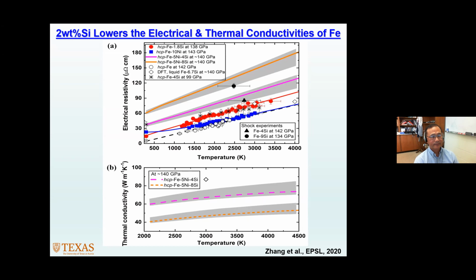And here you're talking about the solid, though, and you need to be considering the fluid, the liquid as well. Yes, I totally forgot to mention that. For Earth's outer core, certainly we need to consider the melting effect on the electrical and thermal conductivity. We made an assumption based on theoretical calculations by Ron Cohen, and the change there is about 5 to 10% also. Okay, good. Thanks. I believe Rick Secco also has some even newer data across melting, but at relatively low pressure conditions.